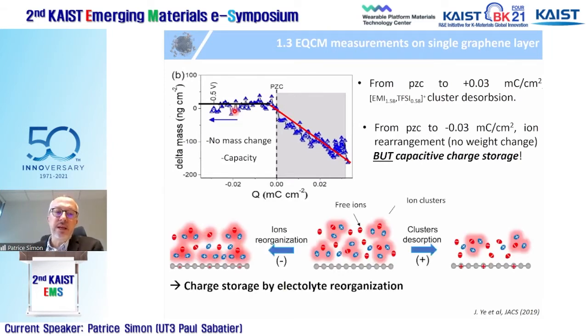And this is really interesting, and it was an unexpected result. What we understood by modeling is that when you go to negative polarization, you have cations which are adsorbed onto the surface of the SLG. The EMI cations are adsorbed vertically, and the more you polarize, the more the cations tend to align parallel to the graphene surface. And this is just a charge storage mechanism by electrolyte ion reorganization at the surface of graphene.